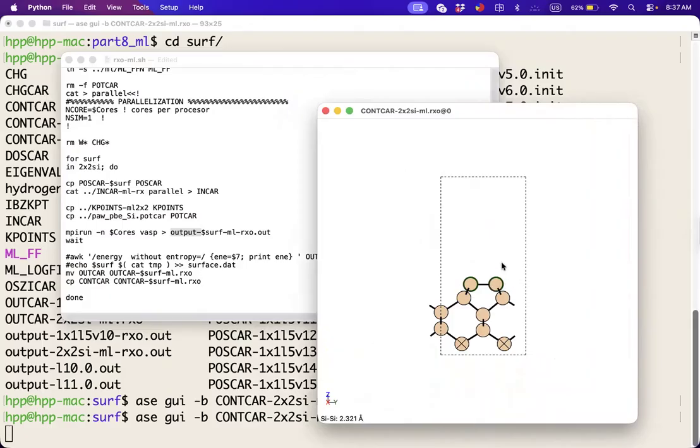What is important from here is that this allows me to check whether my starting guess was good enough. If you put the value too close, you're going to see the machine learning will explode. Your structure might explode, right? So it's better to check this, if you did something wrong about this initial guess, with machine learning rather than doing ab initio. Ab initio will take hours, and after that you find out the structure will explode, and you lost hours of calculations. In this case, in less than a second, you can find out that your initial guess is reasonable. That is the thing that we want to get from this.